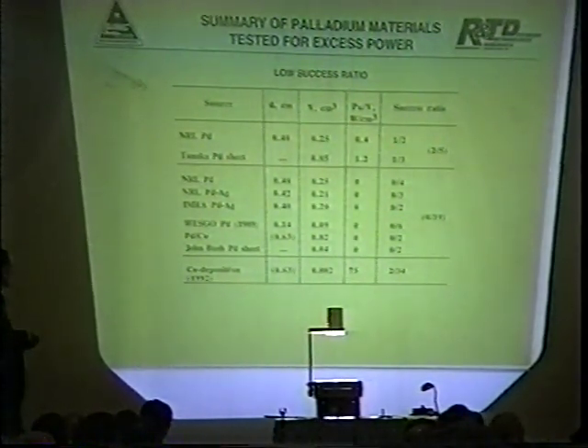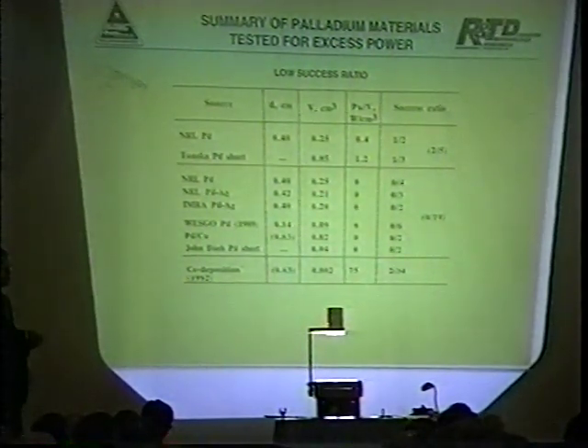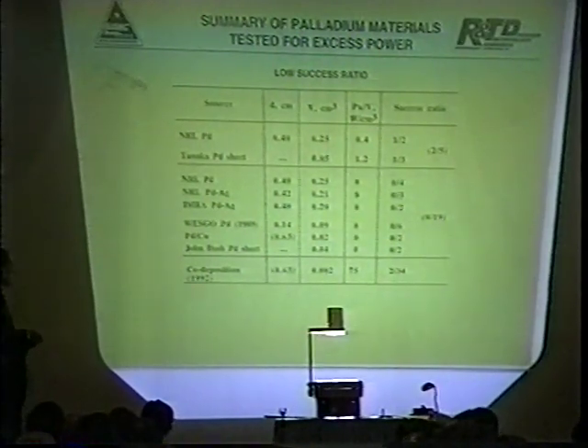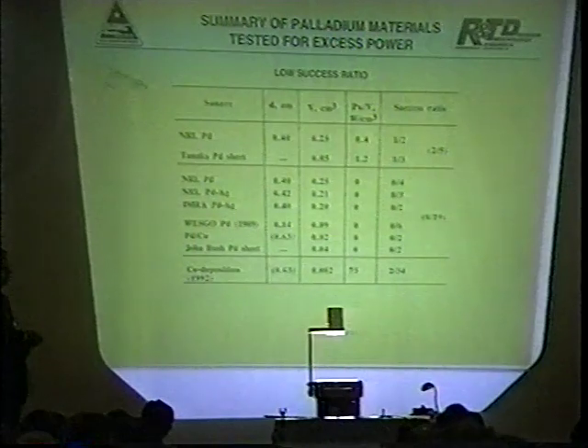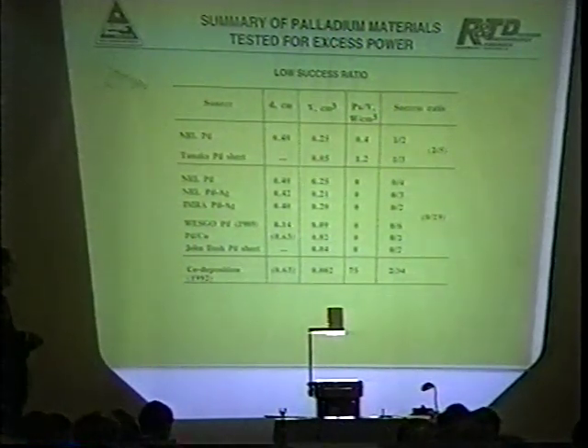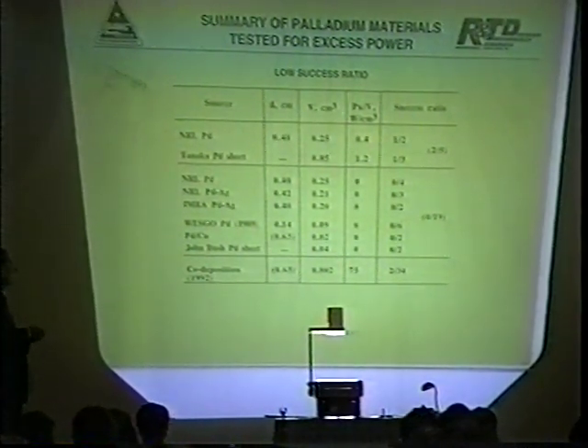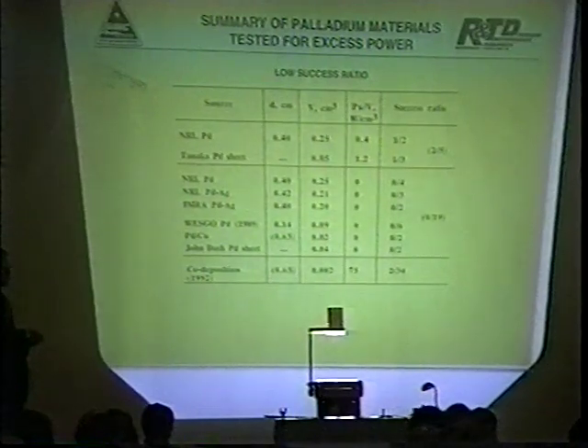Co-deposition is experiments where you plate out simultaneously, plating out a solution and loading with deuterium in the process. Here we have 2 out of 34 that produce excess heat. This is a method by Szpak with another Navy laboratory. The reason we didn't get higher success, I think, is we had such a small volume of plating. Typically, we get 1 watt per cubic centimeter based on the plating volume.